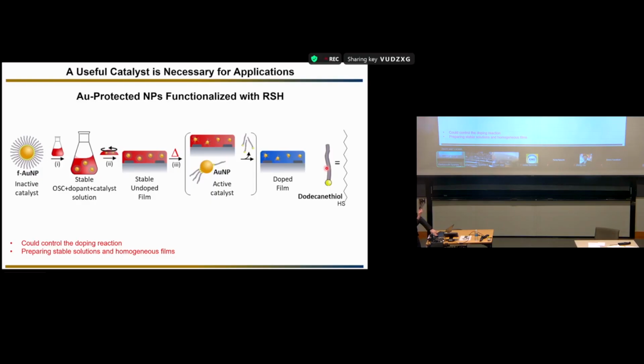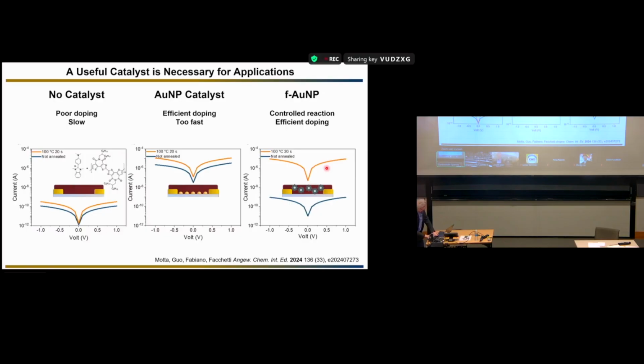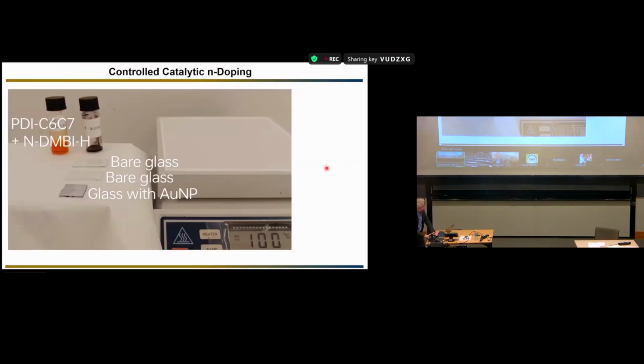The one we did is basically to protect the catalyst, and this is a gold particle, with a shell which decomposes at a low temperature, about 60, 70 degrees. So we can include the catalyst into the mixture, and then only when you heat the film, not at room temperature but at about 60, 70 degrees, can you have the chemistry going on. And let me skip this. It's just reiterating with numbers.